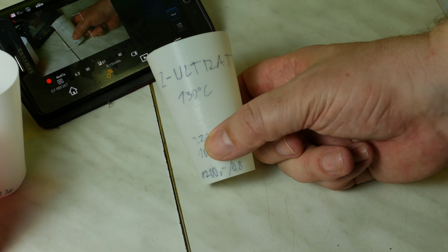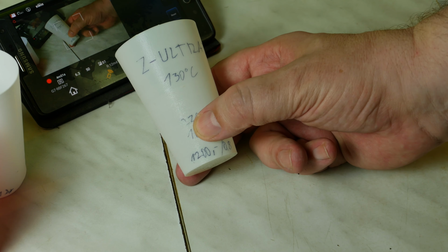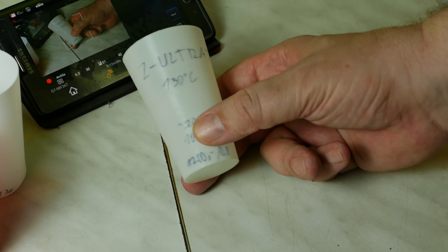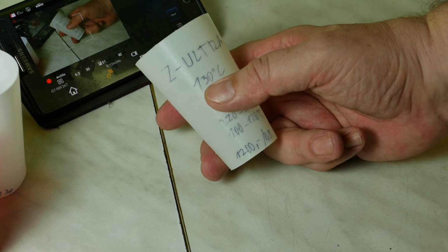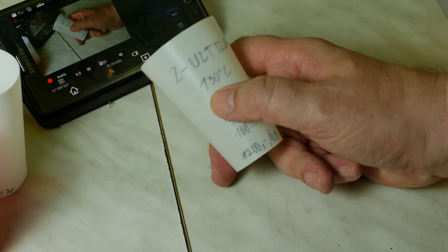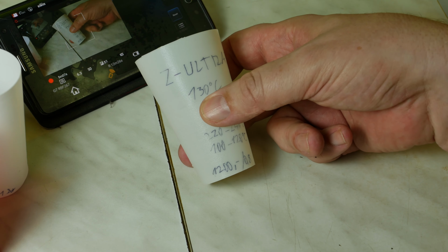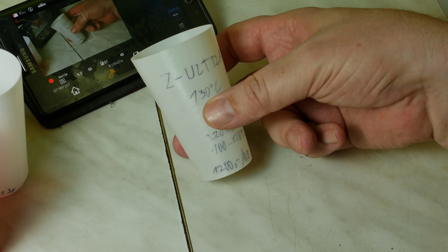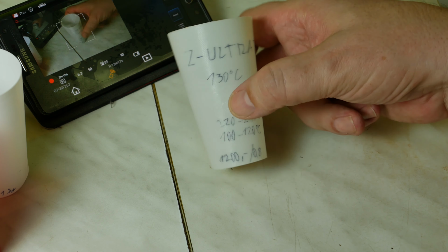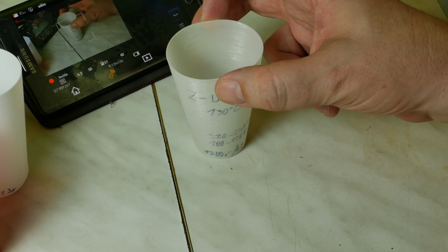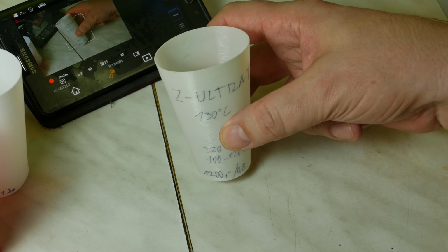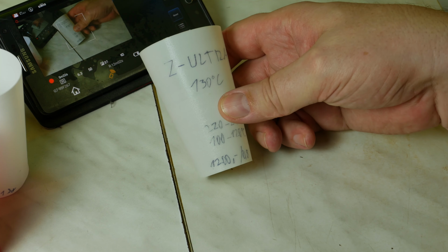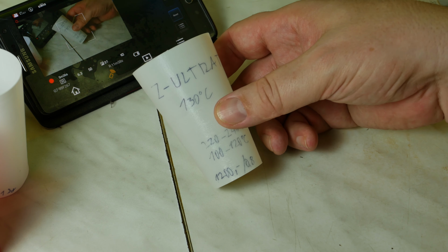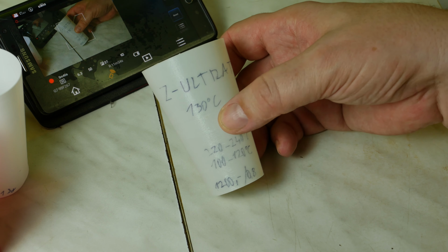And number 1 and gold medal is not Ledecka, but this is Z-UltraT material by Pro3D. This is just the absolute winner. Of course, I did not use 130 degrees of Celsius temperature for this test, but you saw the boiling water actually had no effect on shape, on hardness. Okay, it was a little bit softer and a little bit more flexible, but much better than any other material from this test. Yes, and again you can use it without any annealing process and further complications.